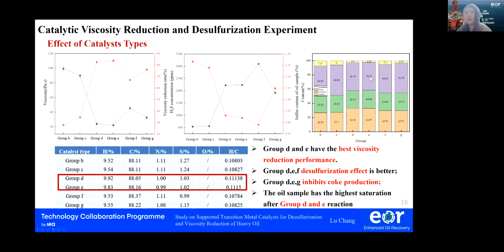This figure shows the quantity change of SARA of the oil sample. We can see that groups D, E, and G have relatively good coke production inhibition performance, because the content of asphaltene, which is the yellow bar, is greatly reduced. And from the element analysis, we can see that groups D and E have the highest hydrogen and carbon ratio, which indicates good heavy oil upgrading performance.